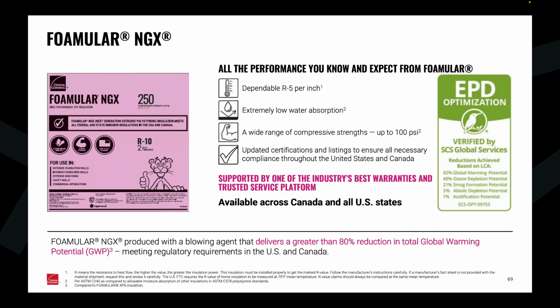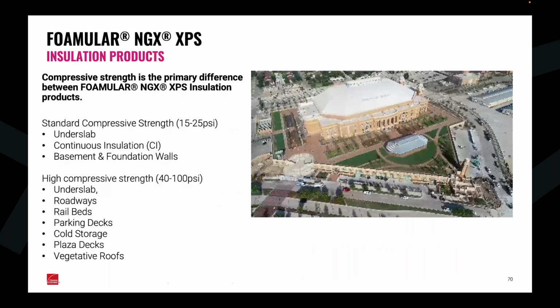So one of the changes that happened in 2020 with XPS insulation is that some of the older blowing agents that were used had a significant impact in global warming potential. So the blowing agent was actually changed, and in this case, we had a significantly lower global warming potential blowing agent, reduced by 80% over the previous one. We're very proud of that, and that product was made standard and available throughout North America prior to it being a requirement, something that we wanted to do proactively as a company.